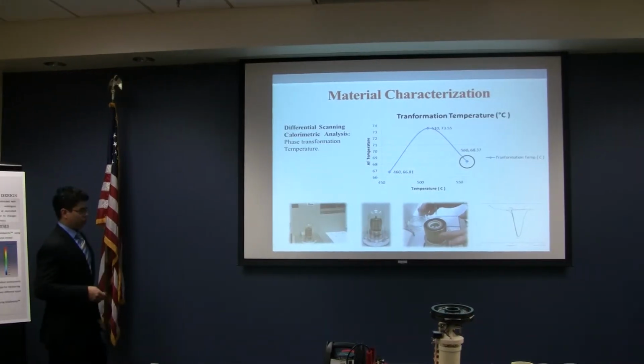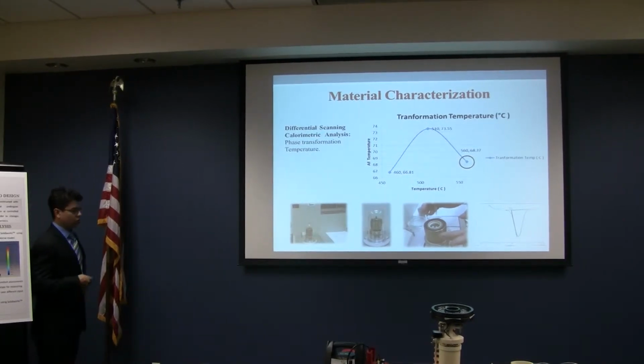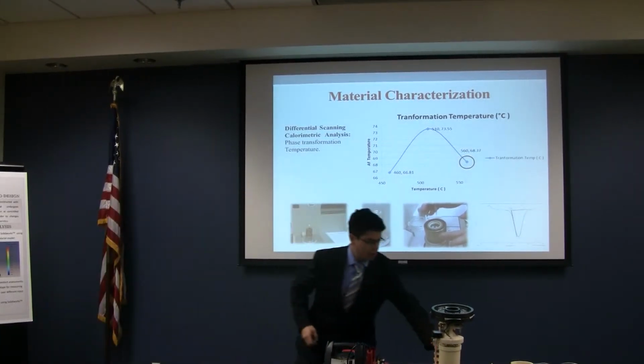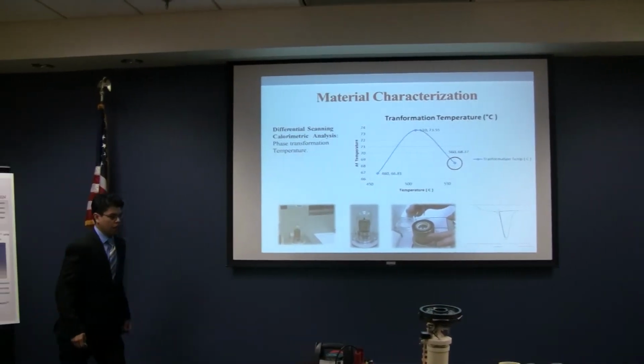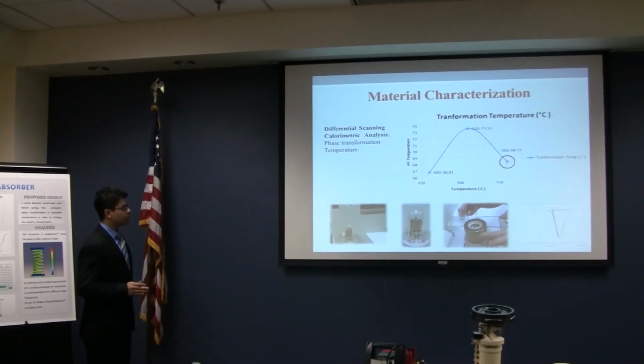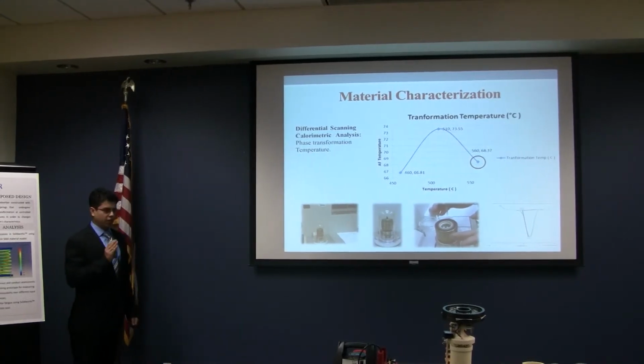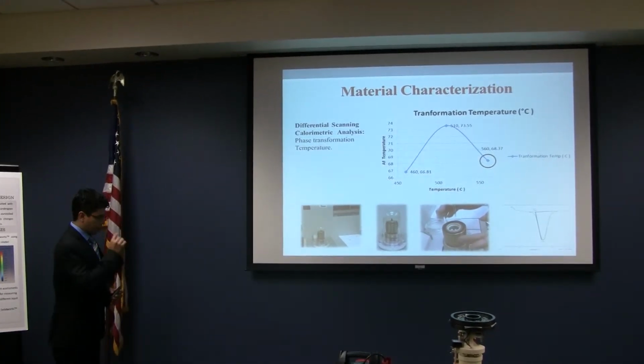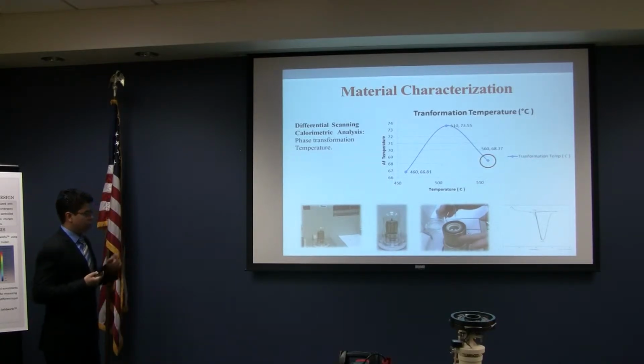The material characterization is going to give us the transformation temperature of the material. Nitinol is very special. It has a solid state phase transformation. This temperature is determined by the process and by the mixture of components. In this case, nickel and titanium. In the shape memory alloy, we can find 51% nickel, 49% titanium. That ratio will determine that. But in order to know, we need to run this through differential scanning calorimetry.